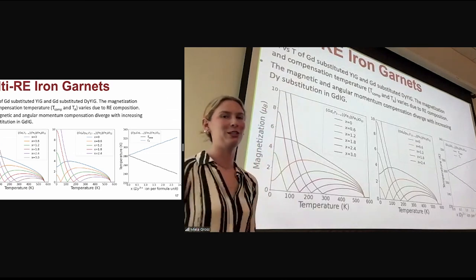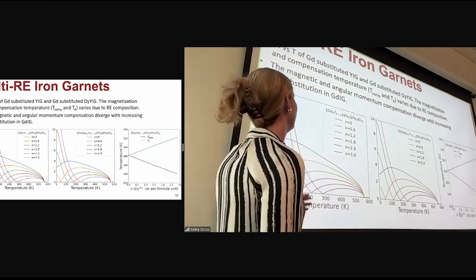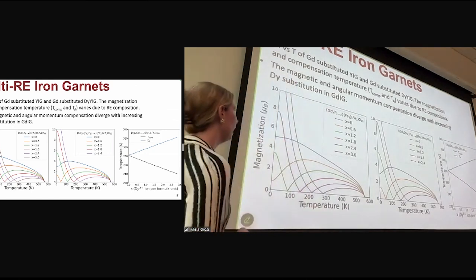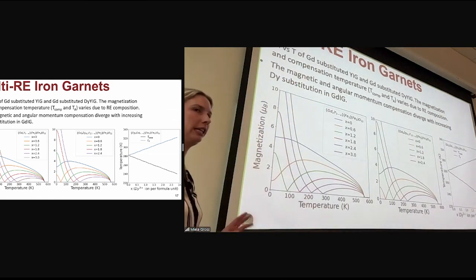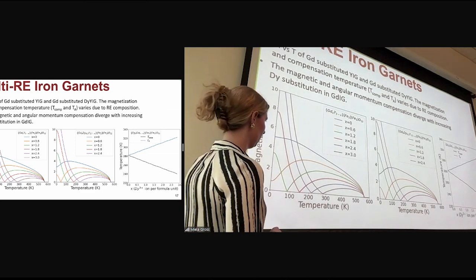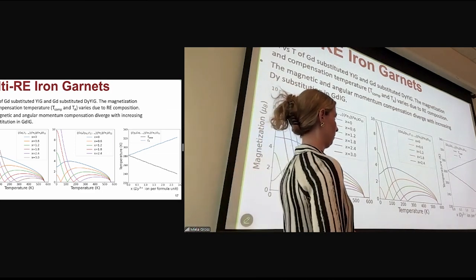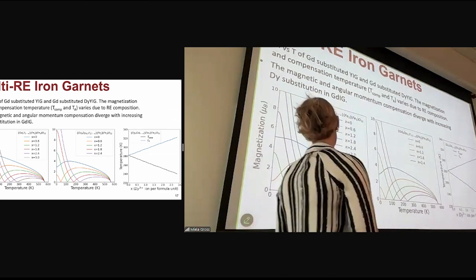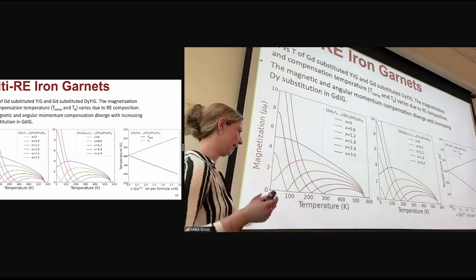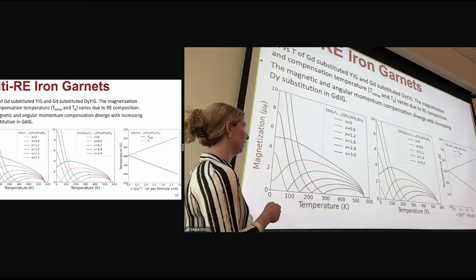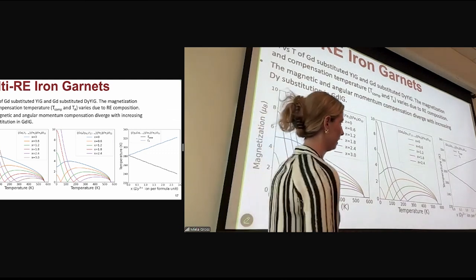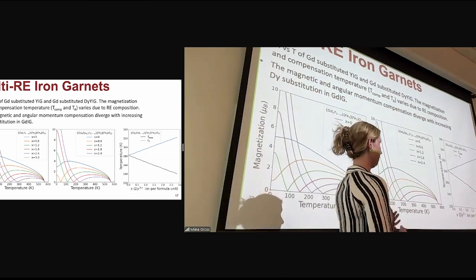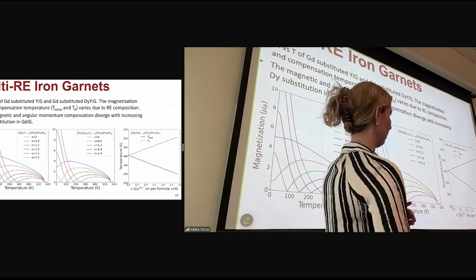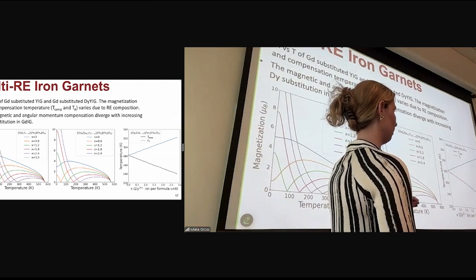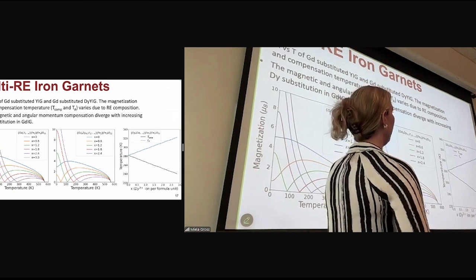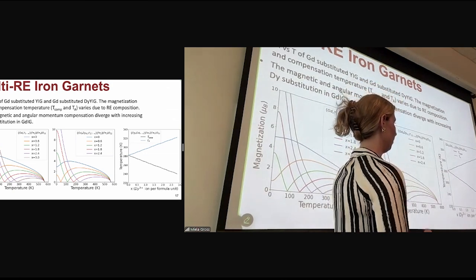So this model can do more than just that, though. It can also account for multi-rare earth iron garnets. So here I have gadolinium substituted yttrium iron garnet, or YIG, for various amounts of gadolinium substitution. And then I have gadolinium substituted dysprosium YIG. And you can see that this compensation temperature, or the antiferromagnetic state, varies as a function of your rare earth substitution. And I modeled that a little more clearly on the right here. Looking at dysprosium substituted gadolinium iron garnet, we see the compensation temperature of the magnetization and the angular momentum compensation temperature diverge as your amount of dysprosium substitution increases.